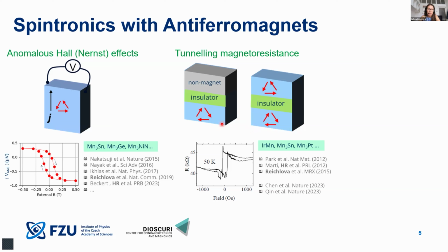during the last 15 or 20 years, it was shown that this tunneling anisotropic magnetoresistance can be present also in compensated systems. This was work which we did already a long time ago, but in principle it relied on the fact that an antiferromagnetic material, in that case iridium manganese, can exhibit some sort of anisotropic magnetoresistance. And the anisotropic magnetoresistance of this layer is then detected through this insulating barrier in this non-magnetic material such as platinum. And indeed, it can exhibit resistance behavior depending on the orientation of the iridium manganese, the antiferromagnet here on the bottom. So here is an example of such a measurement in iridium manganese platinum. And one can see that a characteristic spin-valve-like signal was observed.